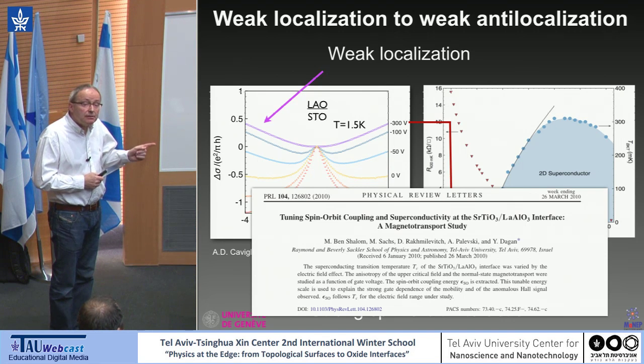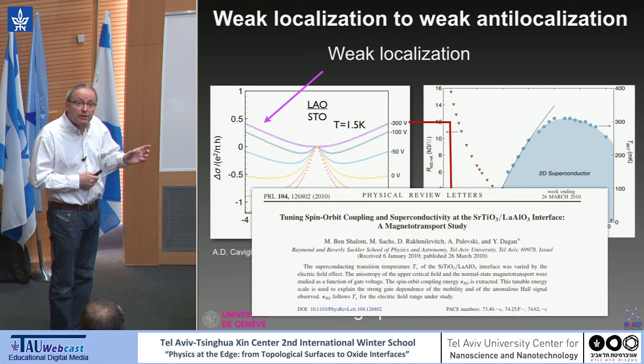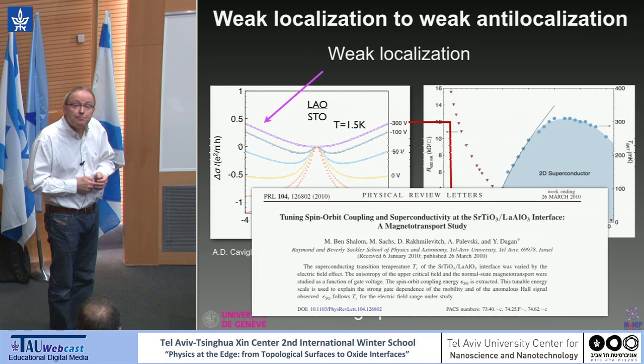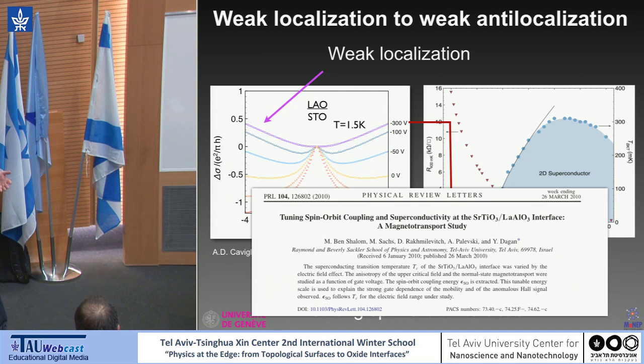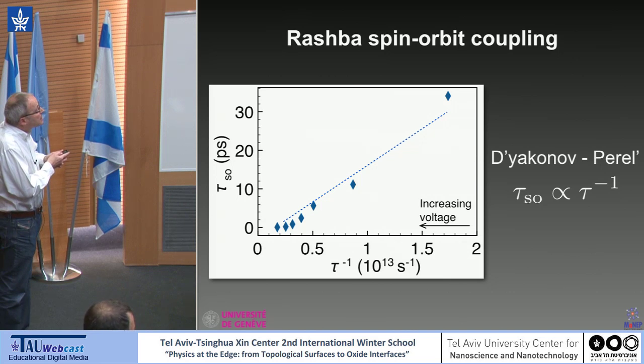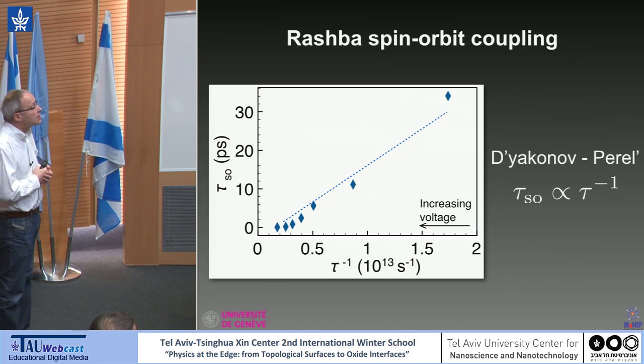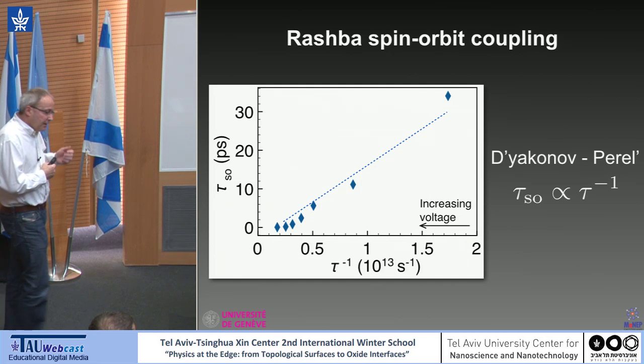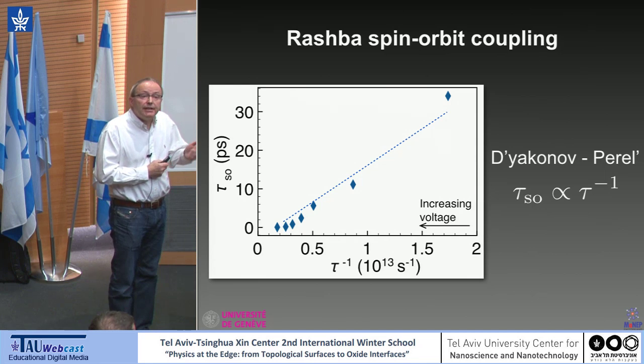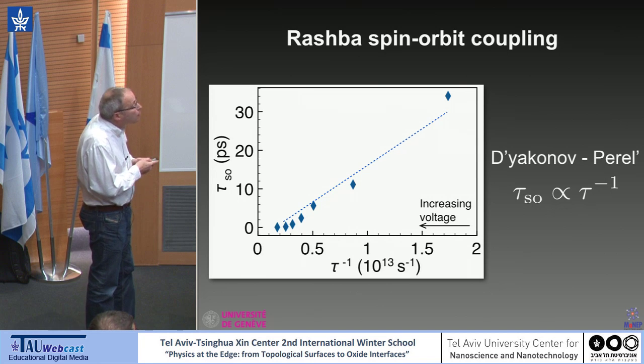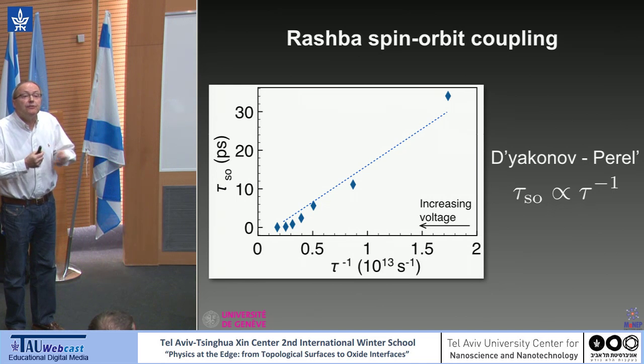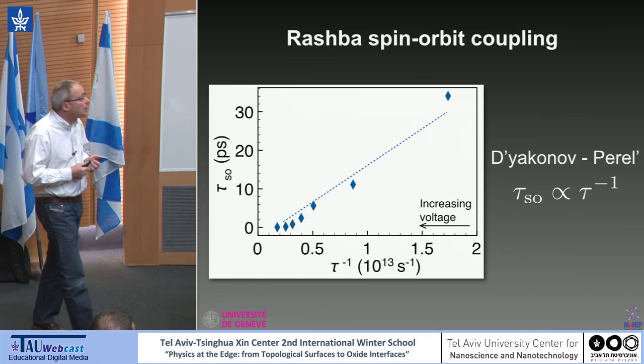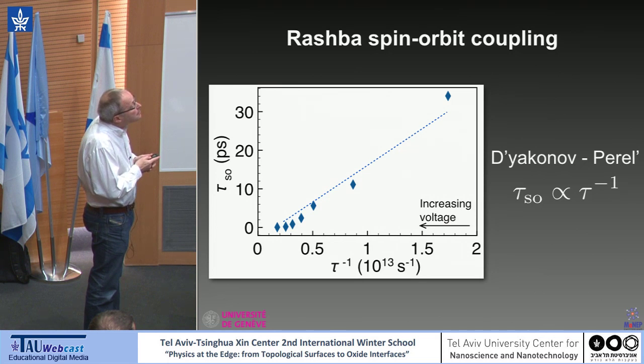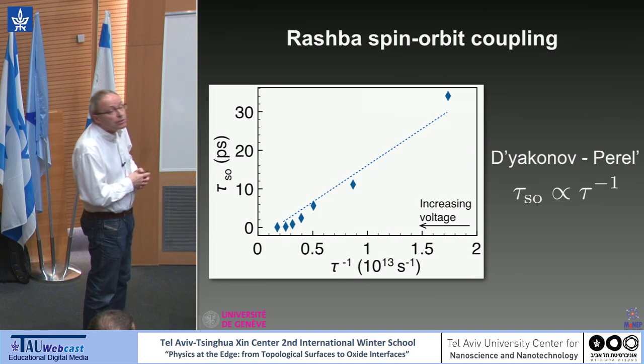Now, there is something important here. What we observe is not an ionic or band spin orbit, but a spin orbit which is linked to the breaking of inversion symmetry that you find at the interface. This is a so-called Rashba type spin orbit. The way to see this is to compare the spin orbit scattering time that you extract from analysis of this curve to the elastic scattering time. If you have an ionic or band spin orbit, the spin orbit scattering time is proportional to the elastic scattering time. The more diffusion events you have, the more chances you have to lose your spin phase. But if it is a Rashba type spin orbit, the relation is a Dyakonov-Perel relation, and tau SO goes as tau to the minus 1. And this is what you see here.